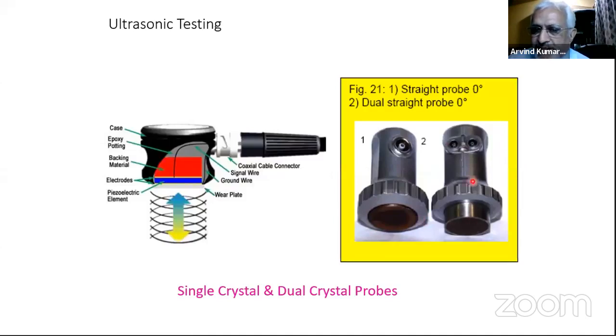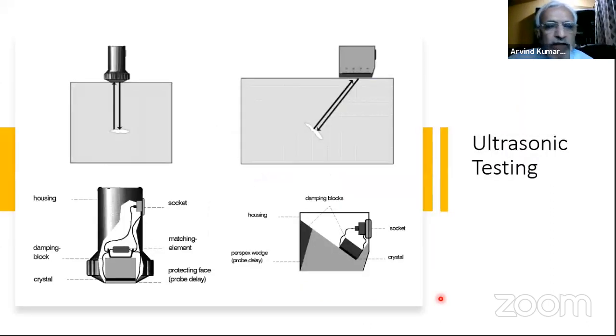The advantage here is that this gives high resolution and is better for checking certain thicknesses, and the dead zone and near field effects are less. But the calibration we need to understand. In the industry, I have seen many people wrongly do the calibration for the TR probe. We need to understand this so that we don't make a mistake.